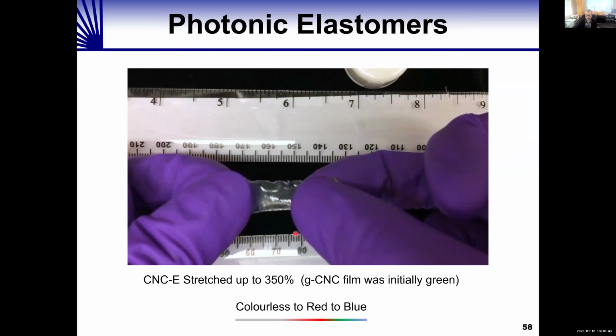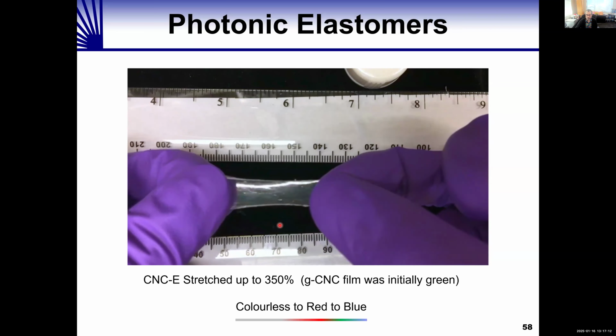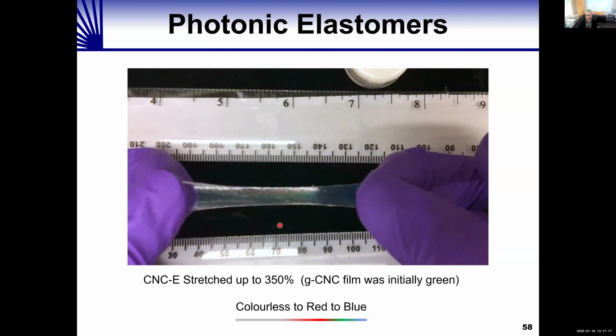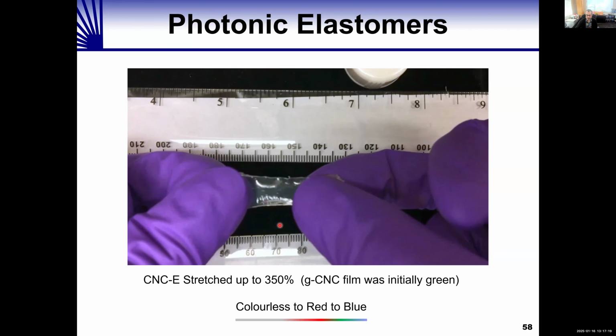So this is a photograph of the elastomer cellulose nanocrystals composite that they produced. Importantly, it has a chiral nematic organization of cellulose nanocrystals with the helical axis coming out of the screen towards you. So I'm going to show you what happens when you stretch this material. Initially it's completely colorless, but as you stretch it, it becomes colored.